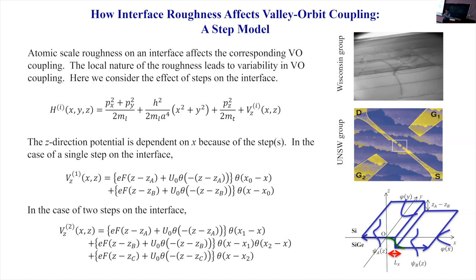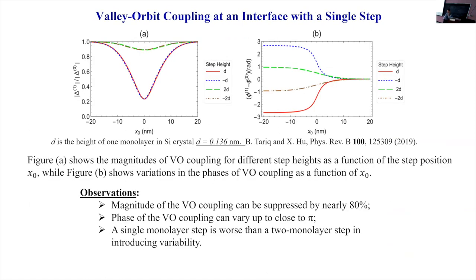For that, you can actually treat it within the effective mass model. So what we did was use a variational approach to simulate the wave function, how it should change around the step. Then we can look at the magnitude of the valley orbit coupling and the phase of the valley orbit coupling, and see how it depends on where that step is within the quantum dot. Let's say the step passes right through the middle of the dot or only goes through the edge.